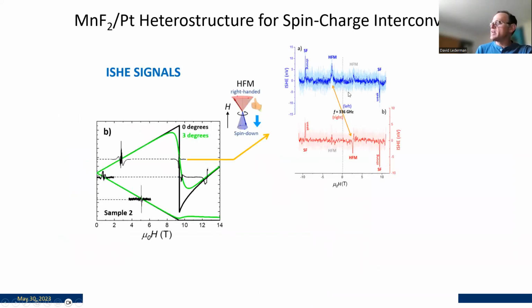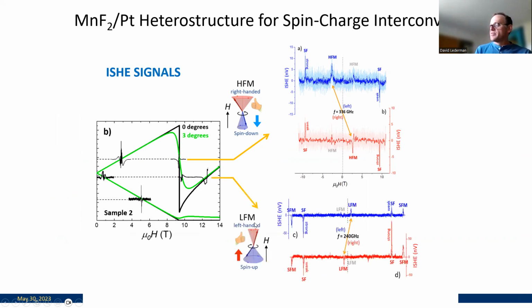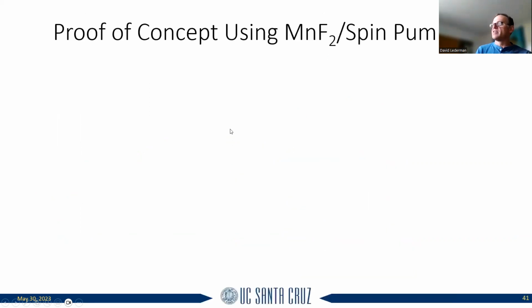These are the signals that we were able to see, and you can see that we were able to detect them with left and right circularly polarized light, and you can see that the inverse spin Hall effect changed from positive to negative field. That breaks the chirality of the radiation, breaks time inversion symmetry. So when you have left-handed polarized light exciting these modes, you see it on the negative side of the field, and here you see it on the positive side of the field. That's exactly what you would expect, and for this other mode you saw the exact opposite. So this was very exciting for us.